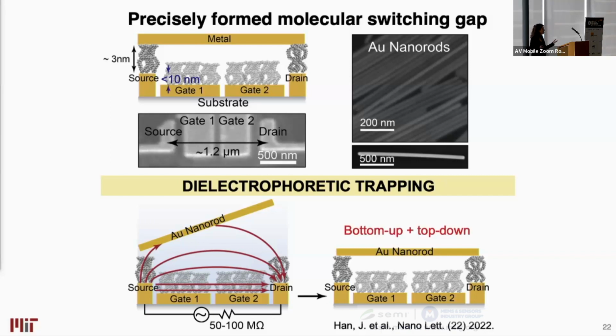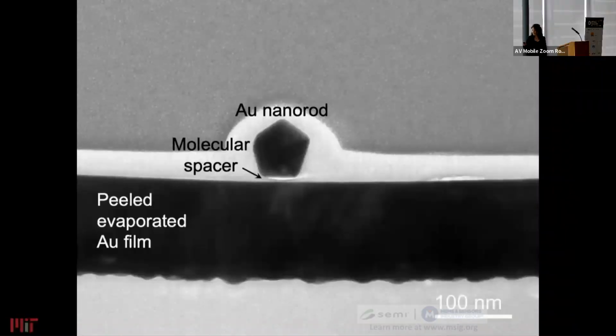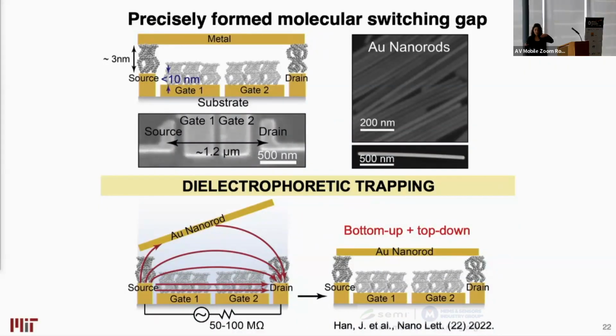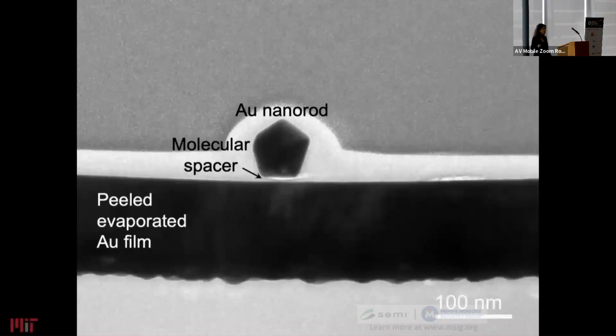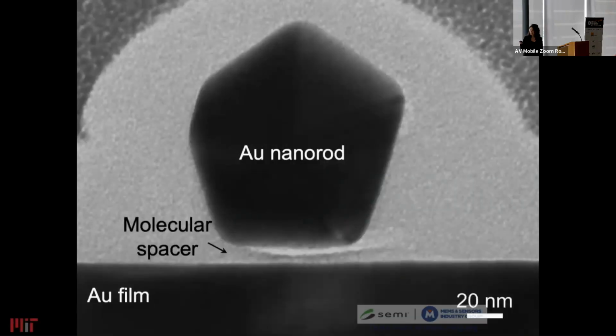Again, an example of how bottom-up and top-down fabrication techniques allow us to achieve devices with unprecedented resolution. Now if I take the device and cut through it and look at it under a high-resolution electron microscope, you can see the gold nanorod top electrode, the bottom electrode, and the planarization that our technique achieves. So this is as-deposited metal surface. You can see how rough it is, and the planarization itself allows us to achieve sub-nanometer smoothness.